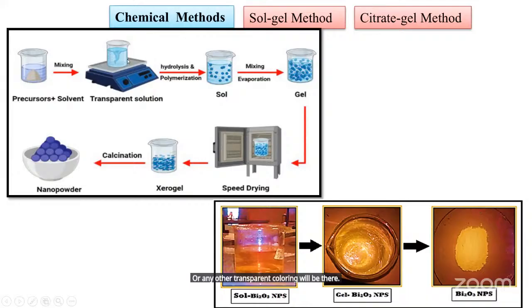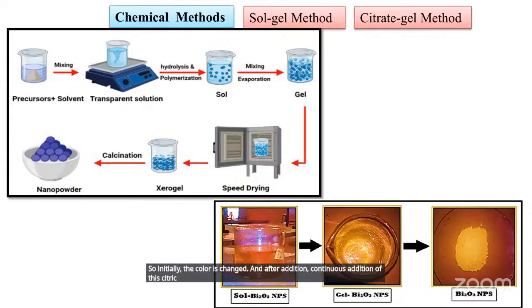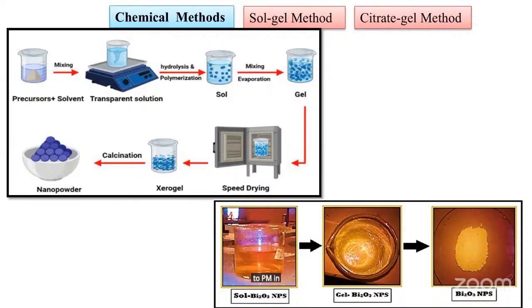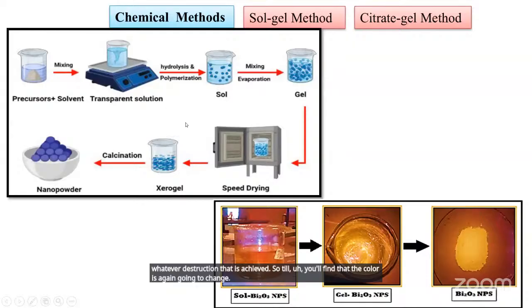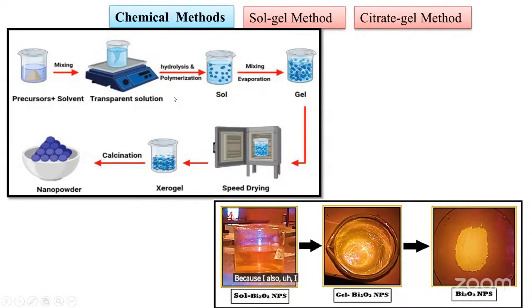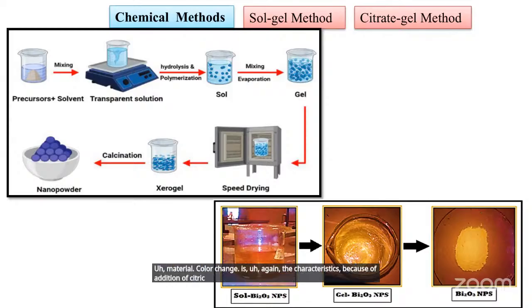But after addition of this citric acid, you'll notice that after some period, 15 minutes or 20 minutes, you'll observe that the color is now going to change. So initially the color is changed, and after continuous addition of this citric acid to a certain limit, 50 ml, 80 ml, whatever the stoichiometry is, you'll find that the color is again going to change in most of the materials. Because I also synthesized many materials by this method and observed the variation in color in the particular material. Color change is again the characteristic because of addition of citric acid, and there is a conversion of this sol into the gel as another stage.